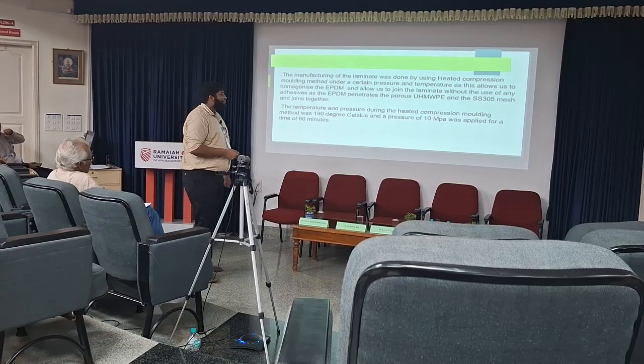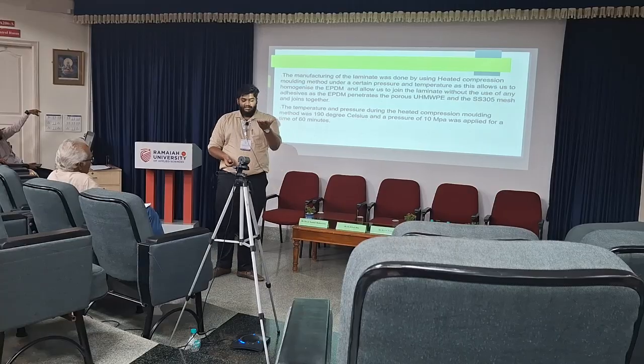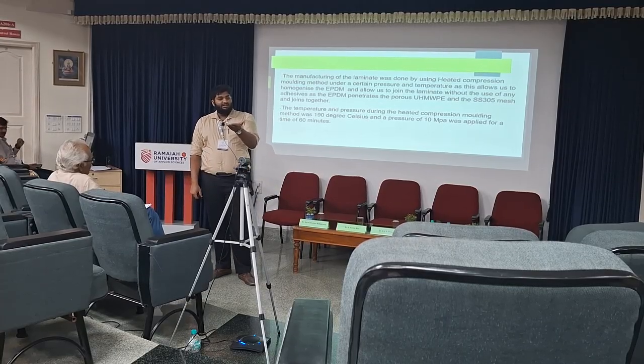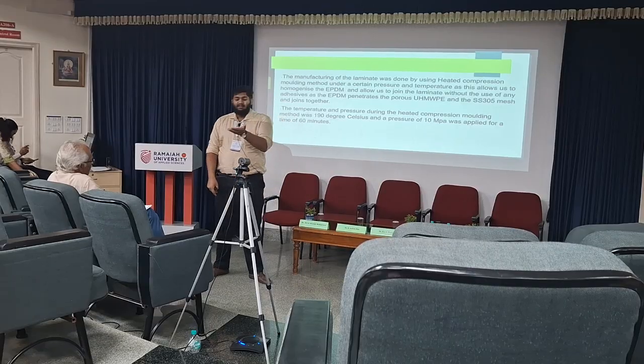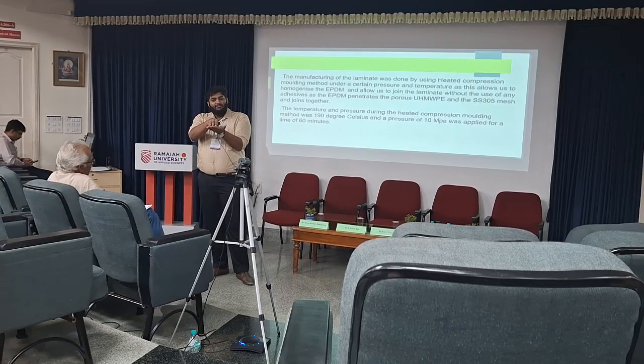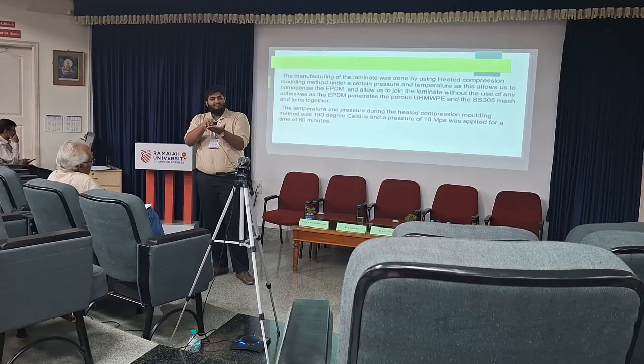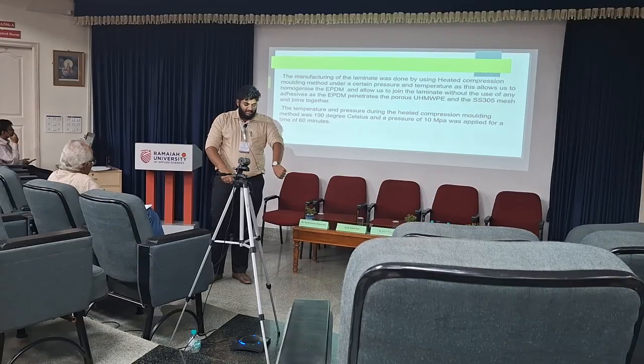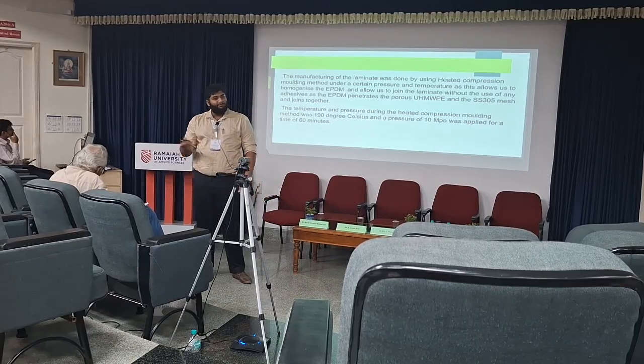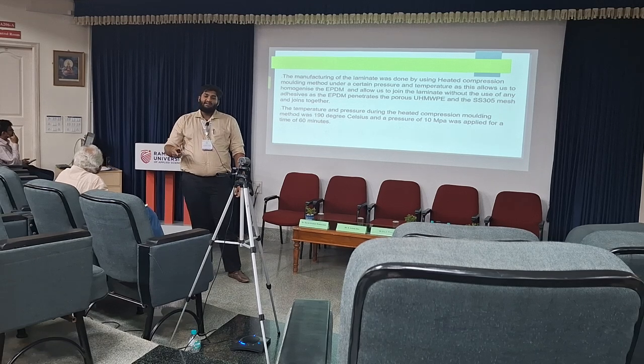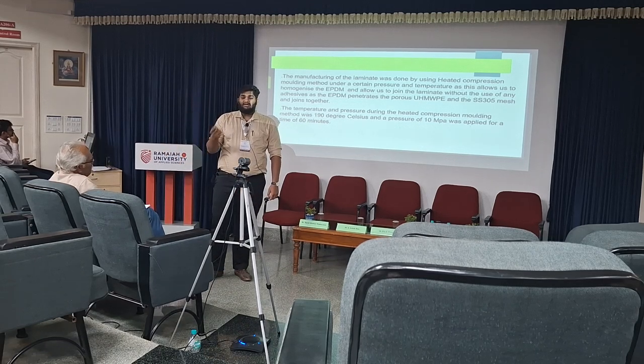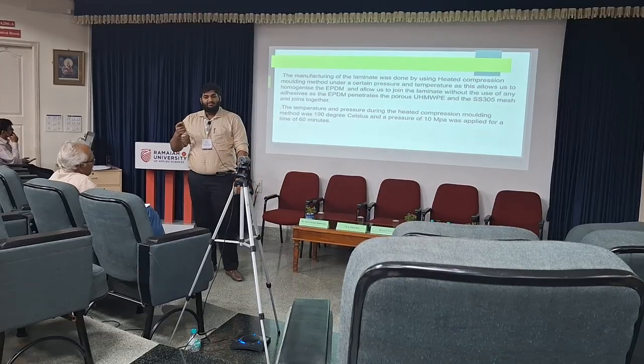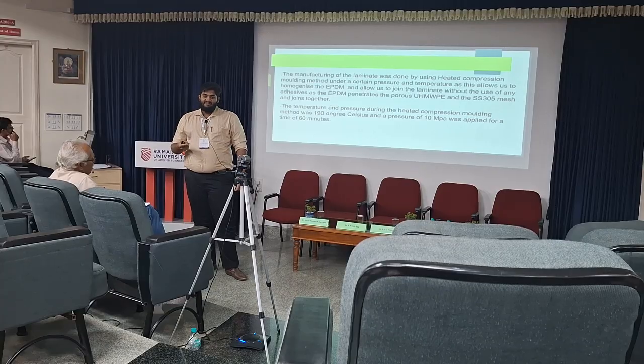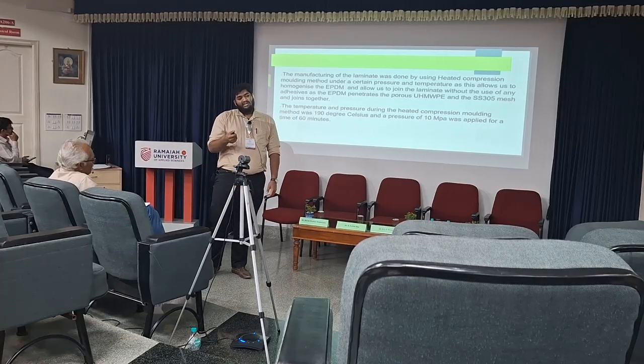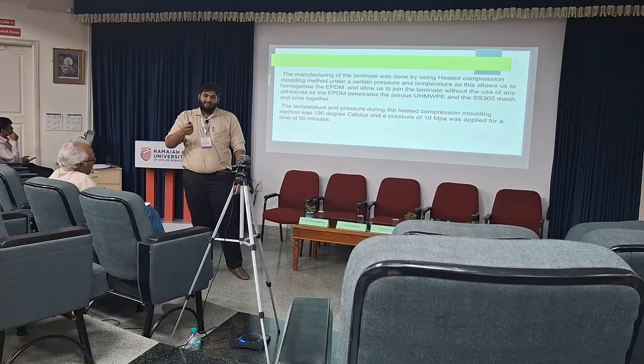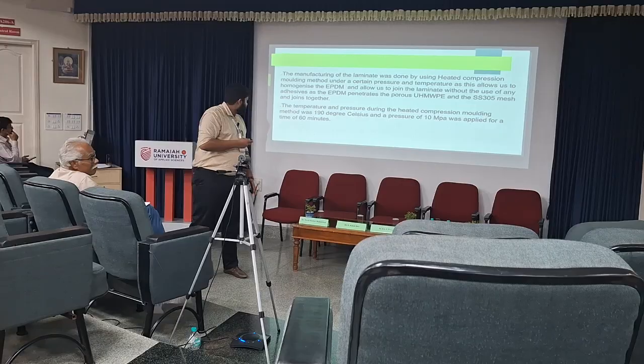And the manufacturing of this was done by heated compression molding. So basically we have the mold which is heated to a certain temperature, in this case 190 degrees Celsius, and then from the top we have another die coming down, and the pressure that this die applies is 10 megapascals. So what we are doing here is we are eliminating the need for an adhesive to form the laminate, because if you add an adhesive, the adhesive might become brittle, it might delaminate at such temperature ranges, variation that is happening. So we are trying to eliminate the adhesive, and just by hot press method we are trying to create a homogeneous layer of EPDM which penetrates the other layers and joins the whole laminate together.